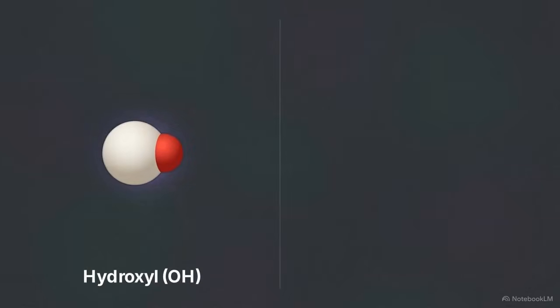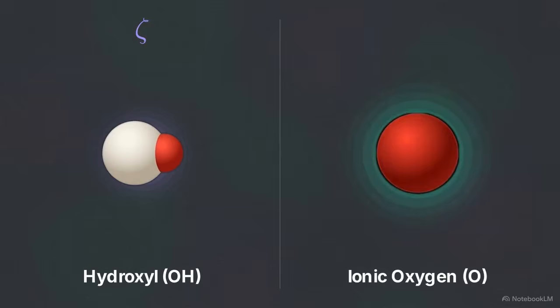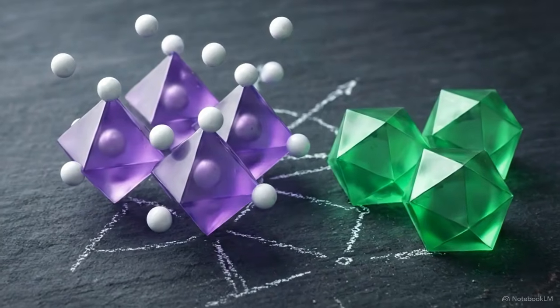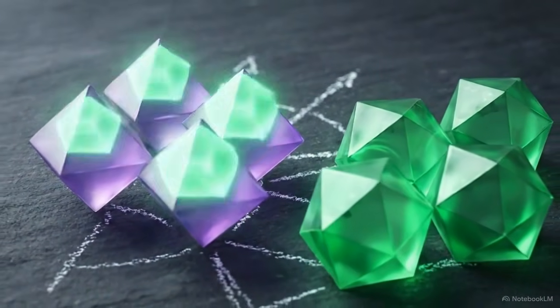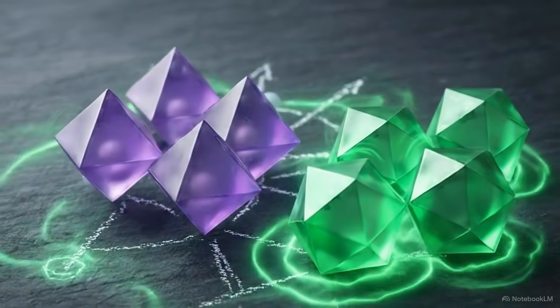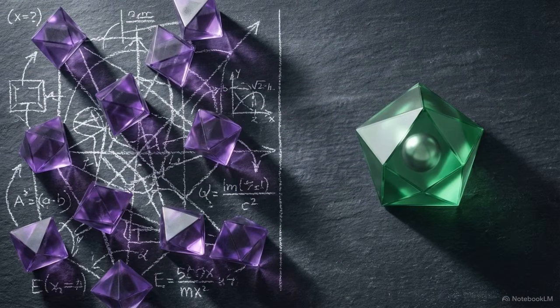Chemically, a covalently bonded hydroxyl ligand has a lower electronic polarizability volume than a purely ionic oxygen ligand. Replacing these hydroxyls with oxygen structurally alters the electrostatic screening capacity of the local neighborhood around the core hole. The temperature-dependent shift reflects a sub-nanometer phase decomposition. The network moves toward lower coordination pure oxygen polyhedra, changing the extra-atomic relaxation energy.